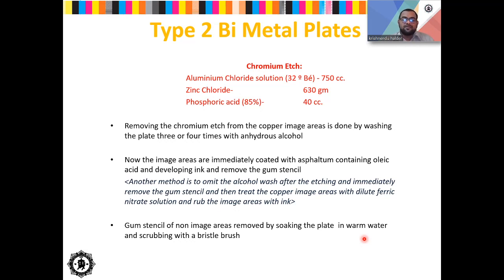So the chromium is removed from the copper image area, and after this has been done, the plate has to be washed with anhydrous alcohol two or three times. Otherwise, if the chromium etch remains present, it will start lateral etching of the non-image metal or the non-image areas. That is why this anhydrous alcohol is required. After this, the image area is immediately coated with asphaltum containing oleic acid and developing ink to remove the gum stencil.